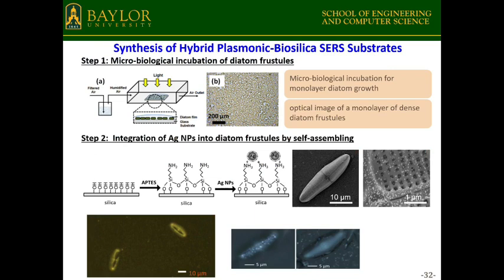And here is what we do. Basically, we used a diatom culturing technique. We feed the diatom with some food. It's just sand, a silicon material, and shine the light, and they will grow. And then you can get high density diatom frustules. And unfortunately, we have to kill those little creatures to remove all the organic part and leave the glass shell there. And then we integrate the nanoparticle at the surface. So you can see this is the SEM picture showing the nanoparticle is deposited at the surface of the diatom. And then we show that you can greatly enhance the light scattering due to the presence of the diatom frustules.